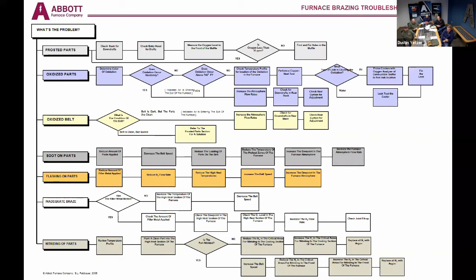The other point about brazing that comes up a lot is joint fit. So when we're pressing a round socket into a round tube, the hole in the tube is oblong. As you flatten that round tube out, you're pressing a round hole into an oblong pocket, and joint preparation and the gap around that joint is exceptionally critical, especially for a lot of high pressure fluid applications. So those are all very common brazing failure modes.